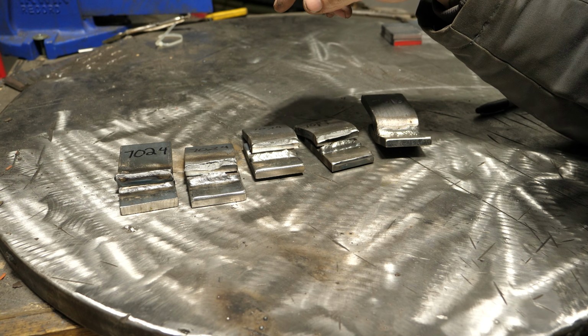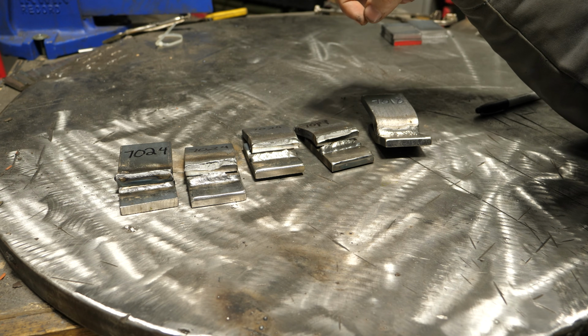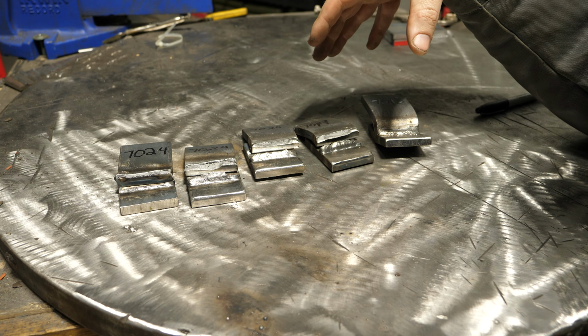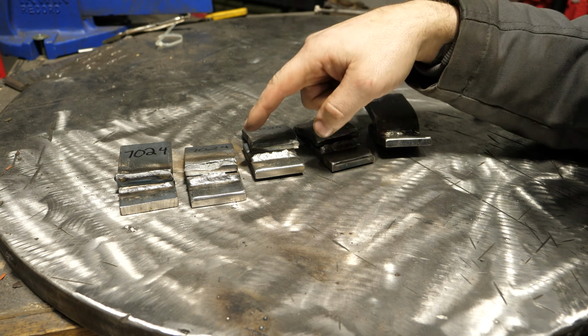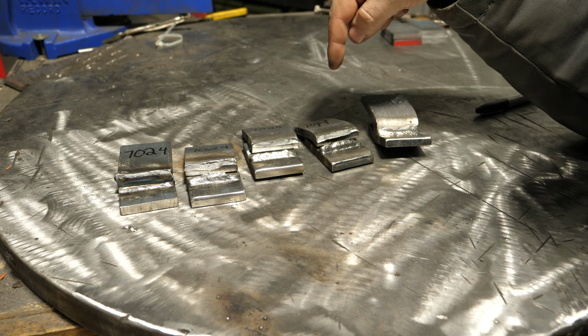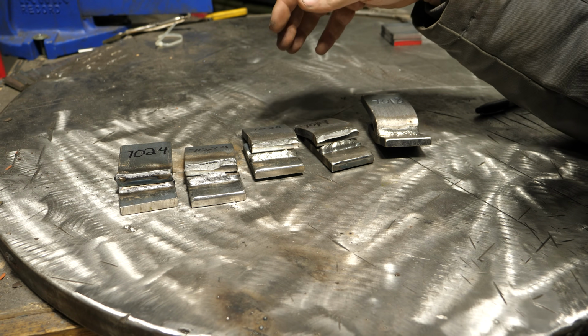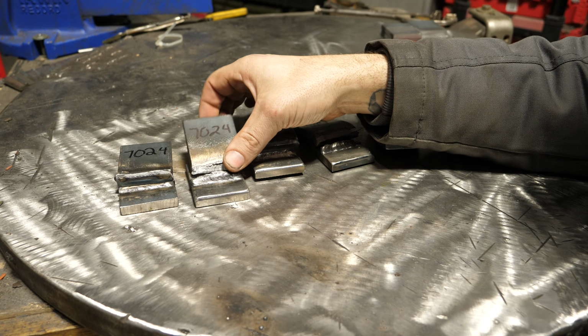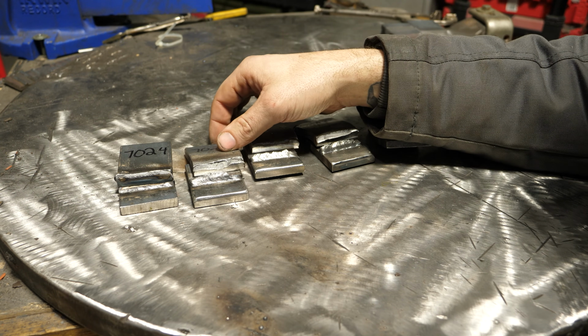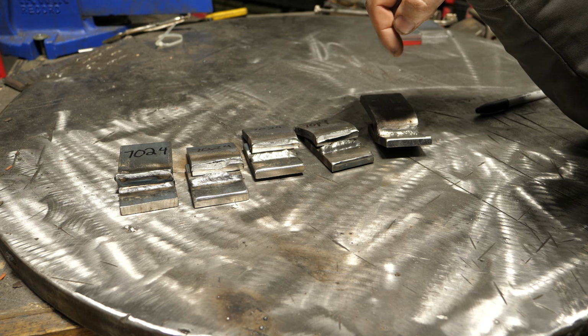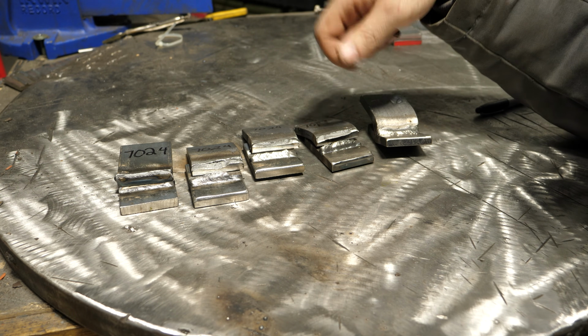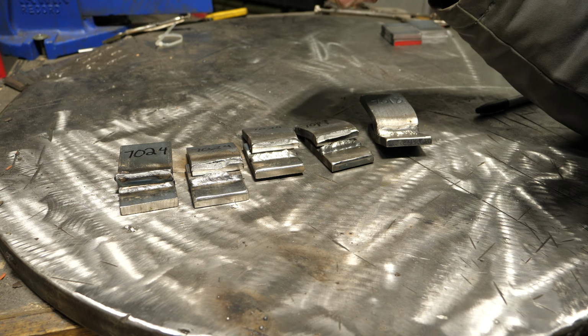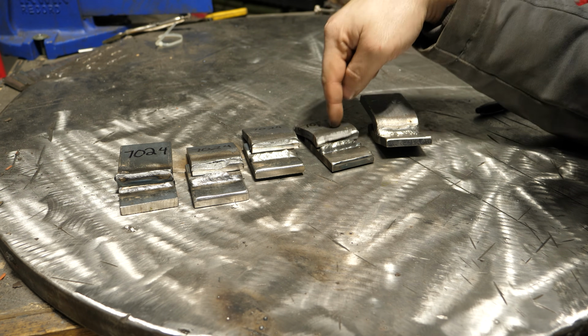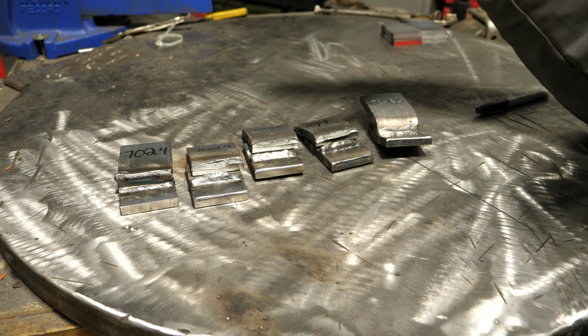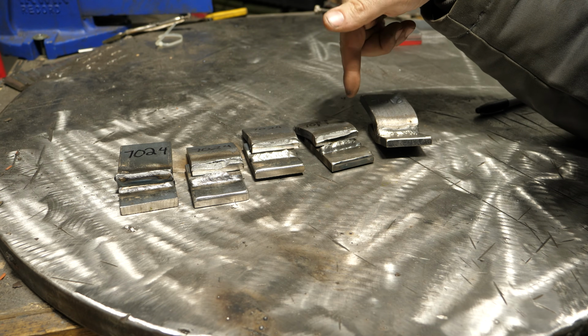So from a standpoint, would I use 70-24 instead of 70-14? Based on my testing in the flat position or on a fillet weld, I probably would use 70-24 over 70-14. The primary reason being, I know that if I can only weld one side of a fillet weld, this will perform better than 70-14 will when it comes to stress towards the face. And then away from the face, it seemed to take a little bit more pressure than 70-14 did as well. So yeah, in a flat position in a fillet weld, I would have no problem running 70-24 over 70-14.